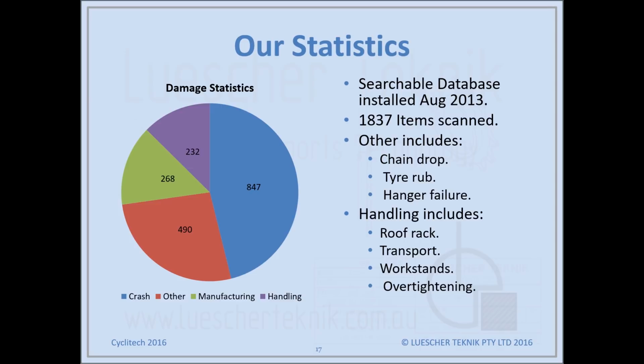The other thing that we found is rear derailleur hanger failure. The replaceable rear derailleur hanger fails and leads to an impact, the derailleur impacting usually the seat stay, but also sometimes the chain stay and causing damage. So they're some of the primary things. The other ones are over tightening parts, roof racks is quite popular as well, and then the baggage handlers in transit and that sort of thing.